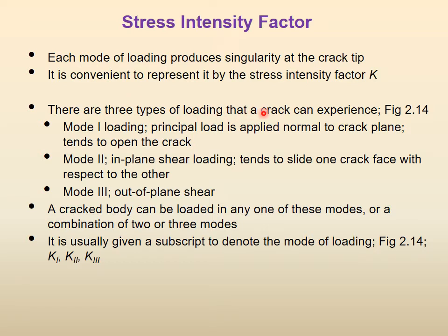And there are three types of loading that a crack can experience. Mode 1 loading, the principal load is applied normal to the crack plane, tends to open the crack. Mode 2, in-plane shear loading, tends to slide one crack face with respect to the other. Mode 3, out-of-plane shear. A cracked body can be loaded in any one of these modes or a combination of 2 or 3 modes.